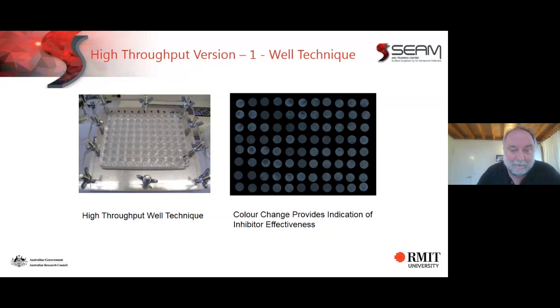This was work that was developed by Paul White at CSIRO, and he used what is called the high throughput well technique. The wells, you put a saline solution in it, and you put the corrosion inhibitor in it. And then you see the color change after 24 hours. Where the color has not changed substantially, there's been very little corrosion, and that's given a low number, indicating that protection of the surface was effective.